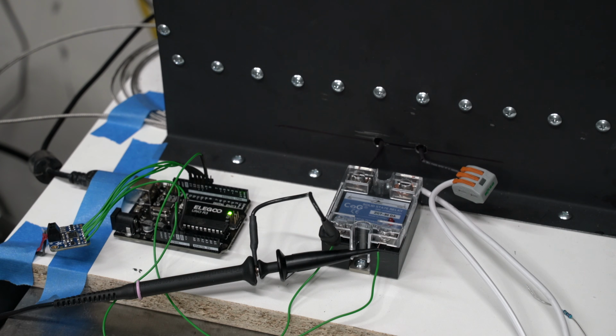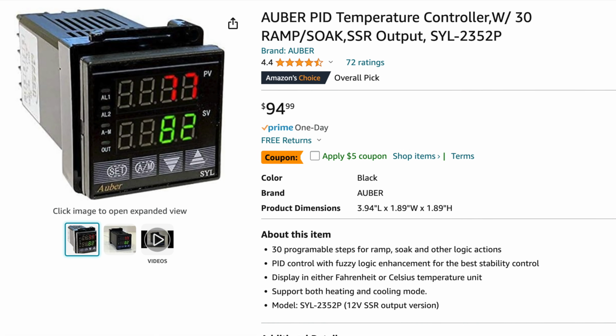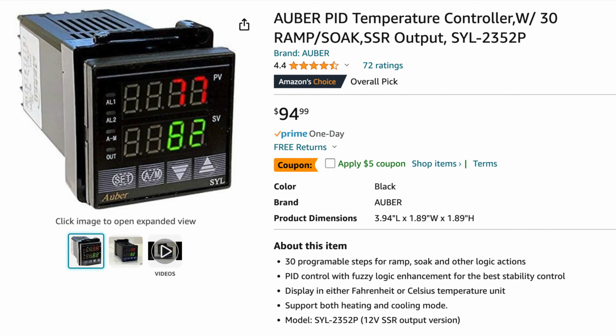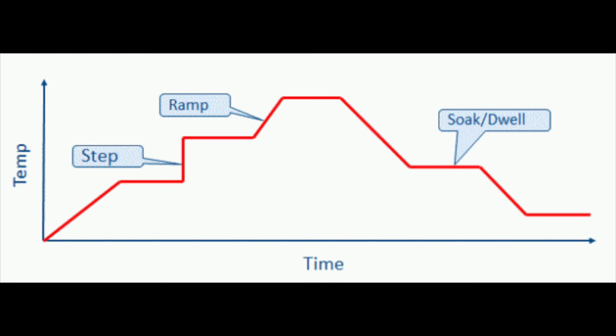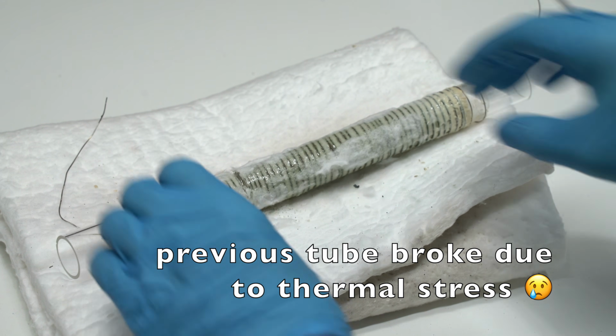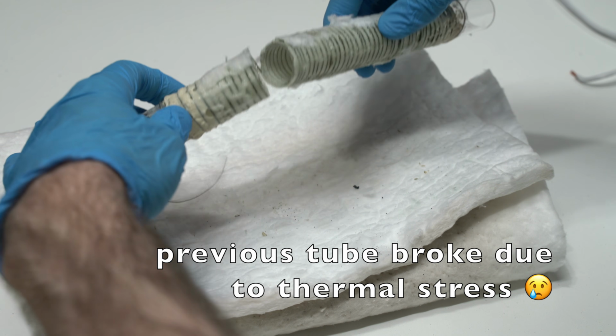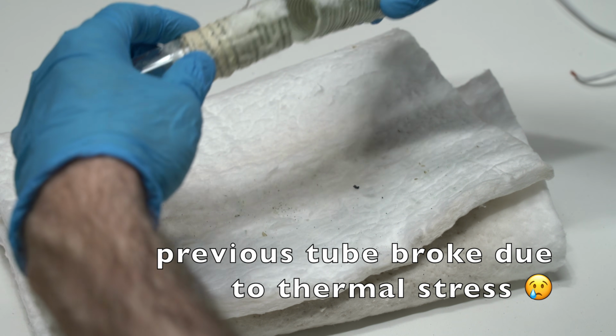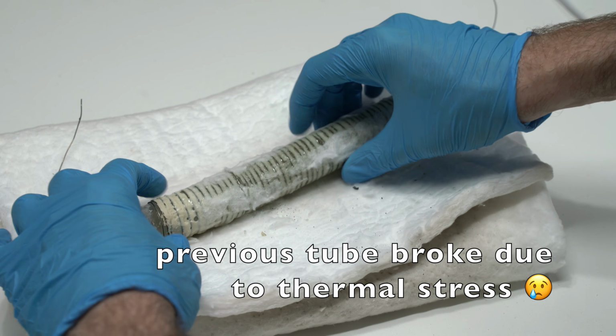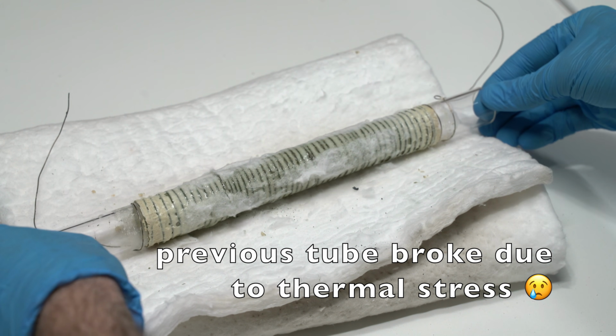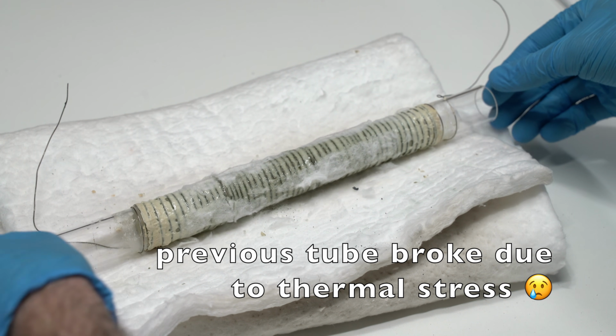Now, up to this point, I haven't really said anything about the electronics I'm using to control this tube furnace. The reason for that is that the correct way to do this would be to just buy an existing ramp soak controller. A ramp soak controller will not only control the temperature set point, but it will also control the rate of change of temperature. This is critically important because, as mentioned before, quartz tubes can't really tolerate a ramp rate any greater than about 30 degrees Celsius per minute. Any greater than that, and you risk the thermal stresses slowly cracking the quartz tube over time.